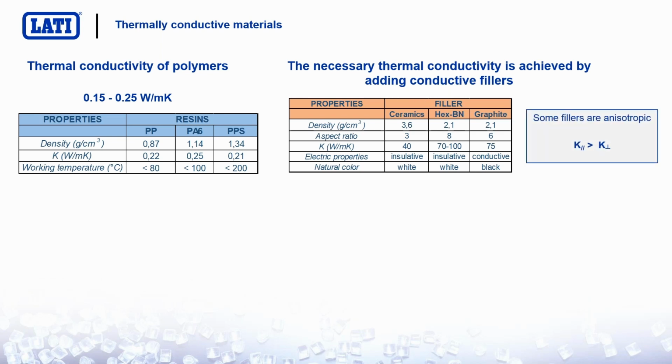Some of these fillers may be anisotropic. That means that the thermal conductivity varies depending on the direction we consider and we measure. Usually the value in the longitudinal direction is higher than the value in the transversal direction of the fillers. This means that these fillers have anisotropic properties, not only thermal properties, but in general are anisotropic.